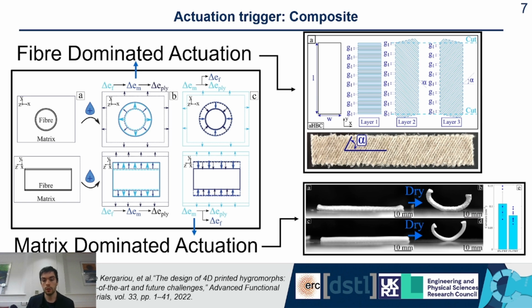For the matrix-dominated actuation, it's a bit different. There's a matrix that wants to expand and contract, and the fiber in the fiber direction does not want to move, and so it's going to prevent the deformation of the matrix in the direction of the fiber. And therefore, if you print with different angles in different layers, the fiber is going to constrain the matrix in different directions, and therefore you can get actuation of your structures.